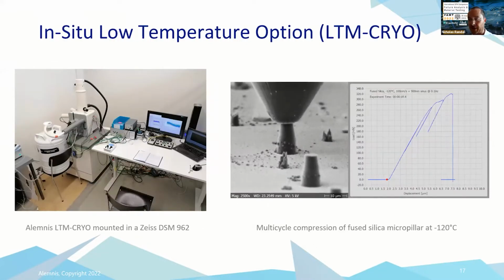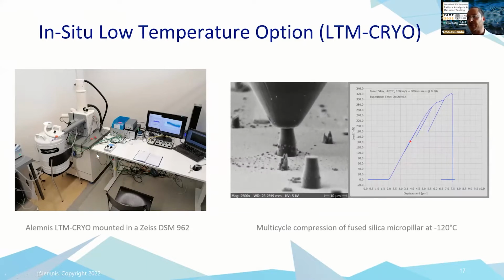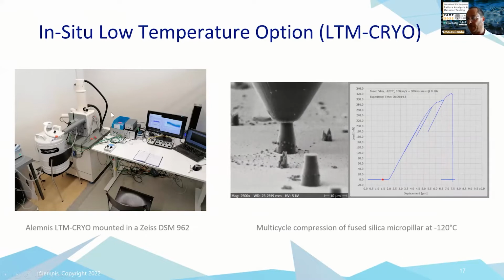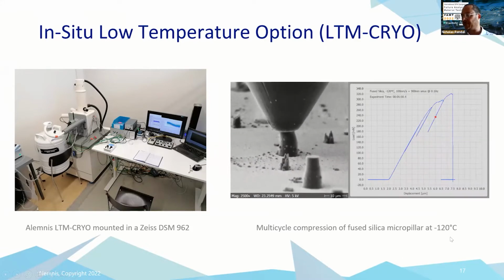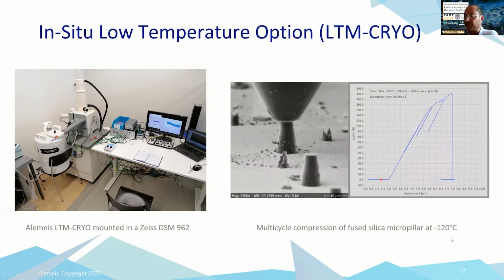This is how we do cryo, so low temperature. So we're actually cooling the system by pumping liquid nitrogen into the SEM chamber. And here we've got a fused silica pillar being tested with a multi-cycle at minus 120 degrees C.